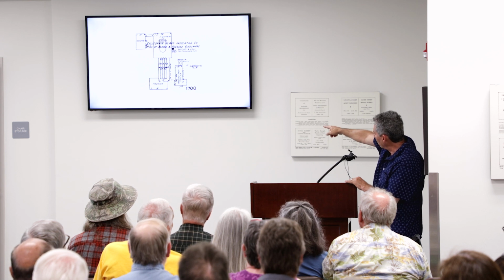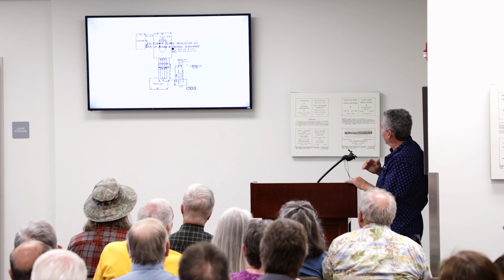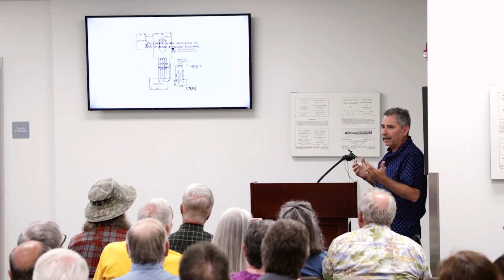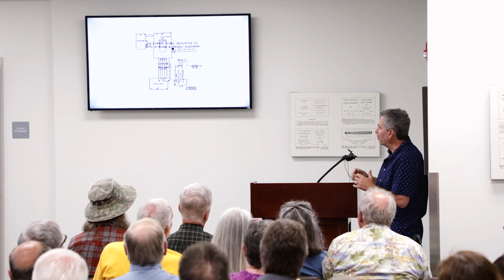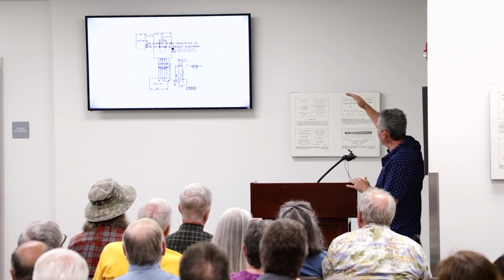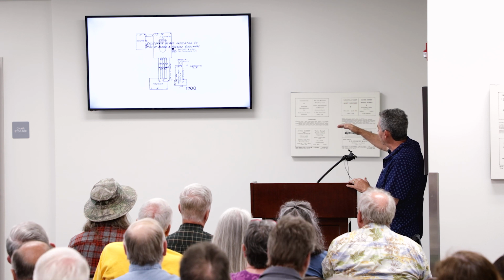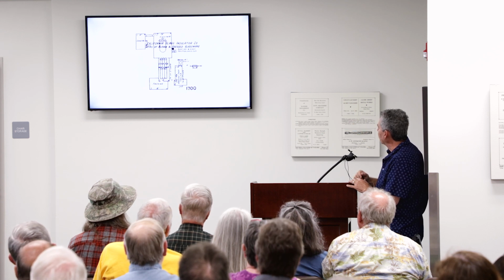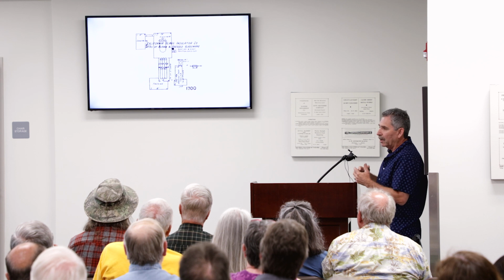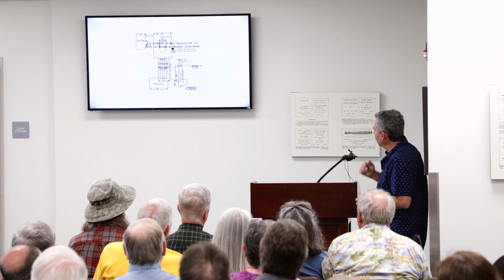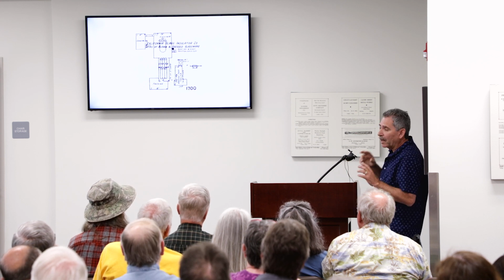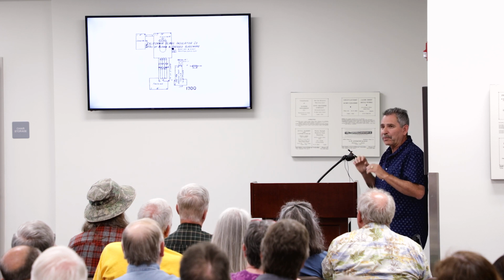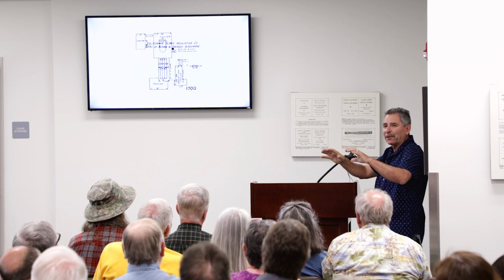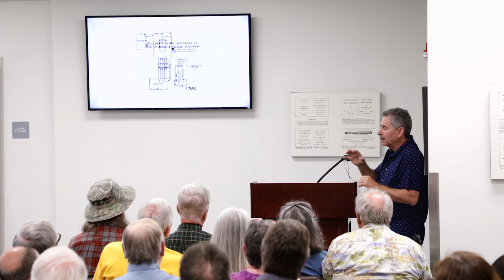end, as you get down there toward where it says packing, and that's where the glass would be taken out of the annealing oven. So 12 to 24 hours for that process, very, very slowly moving the insulators through that annealing oven. Then once they got to the end, that would be air temperature. They'd take them out, and then they claimed that they took the insulators and put them outside and let them sit out there and cure for 3 months.